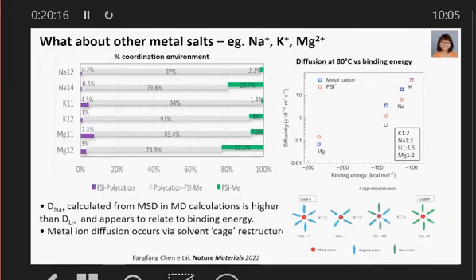So what we found here was that in the magnesium systems, where the binding energy is very strong to the anion, you actually had a lot less of the co-coordination environment and more of the salt, if you like, molten salt environment. And that correlates to a low diffusivity when you measure on the right-hand side the diffusion coefficients that we calculate from the mean square displacements. And the magnesium has the lowest. And then we see that the sodium 1:2 has a really high co-coordination environment, and that correlates to a high sodium diffusivity. In fact, the metal ion is significantly more diffusive here than the anion is in the MD simulation. And also what's really interesting is almost a factor of 10 higher than the lithium equivalent.